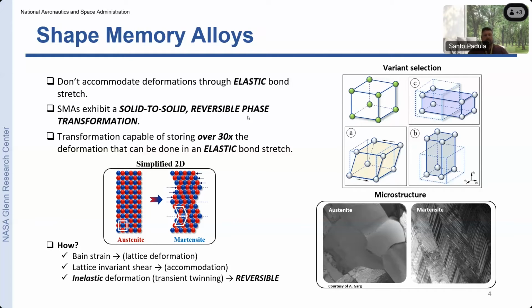That motion, since it's not just related to bond stretch, is capable of doing over 30 times the deformation that we could do in an elastic bond stretch in a conventional metal. And this opens up a new window of opportunity for us to utilize these much larger reversible strains within the structure to completely change the way we design a structure.